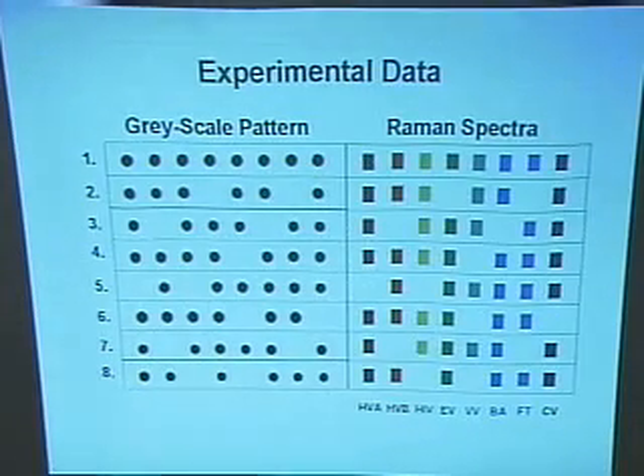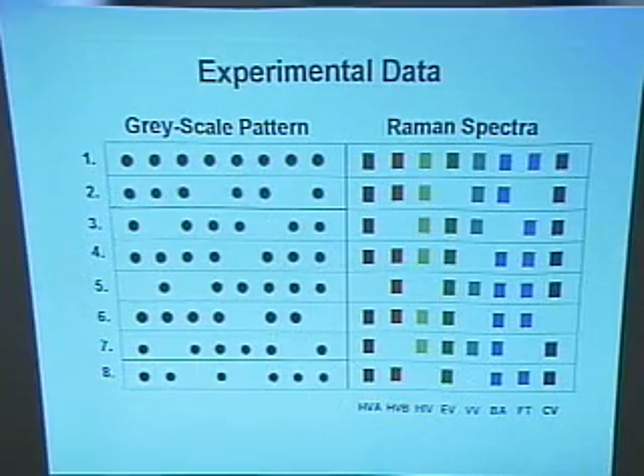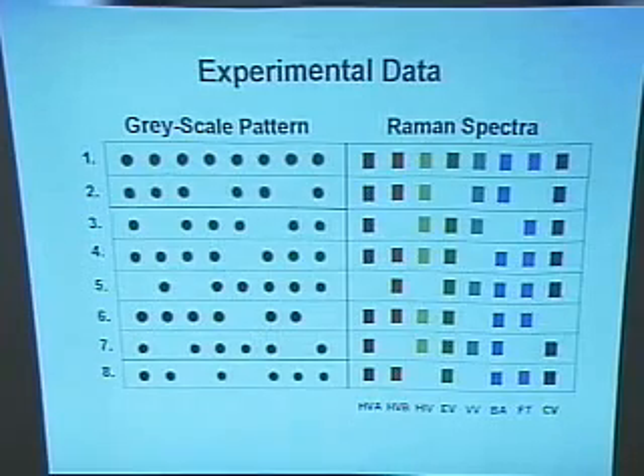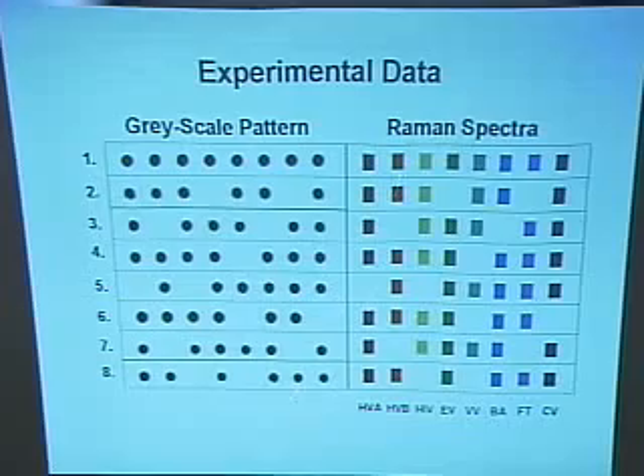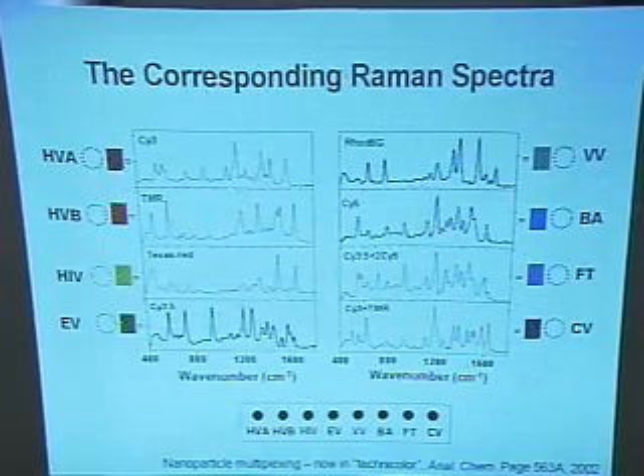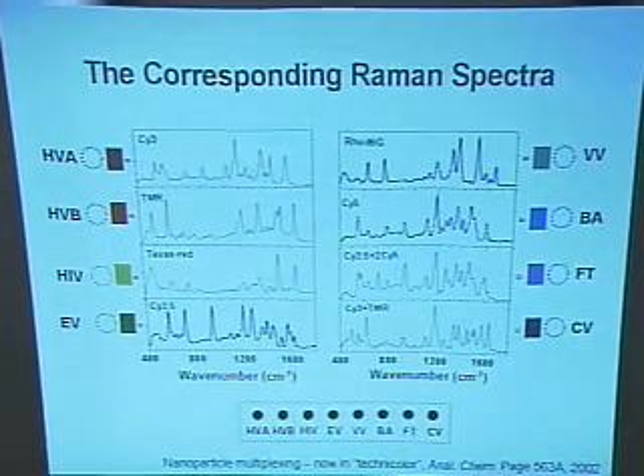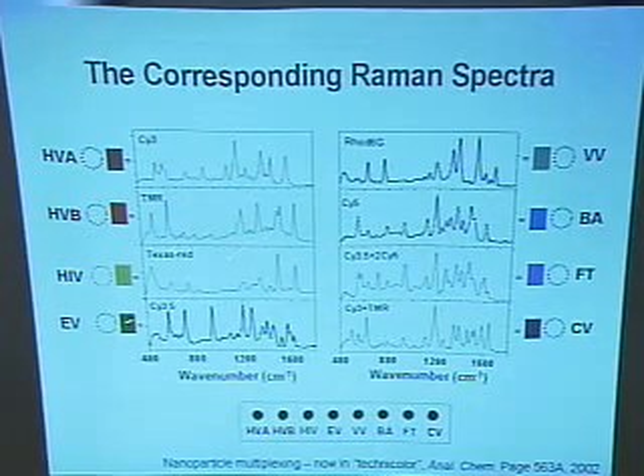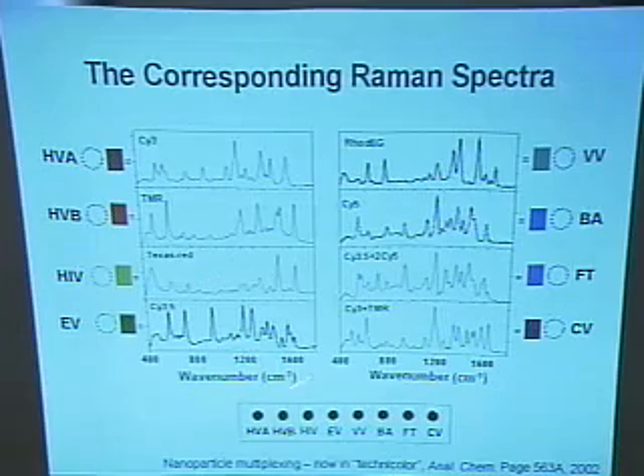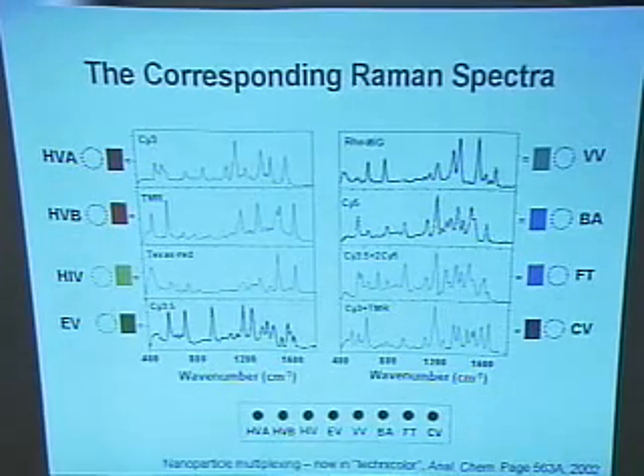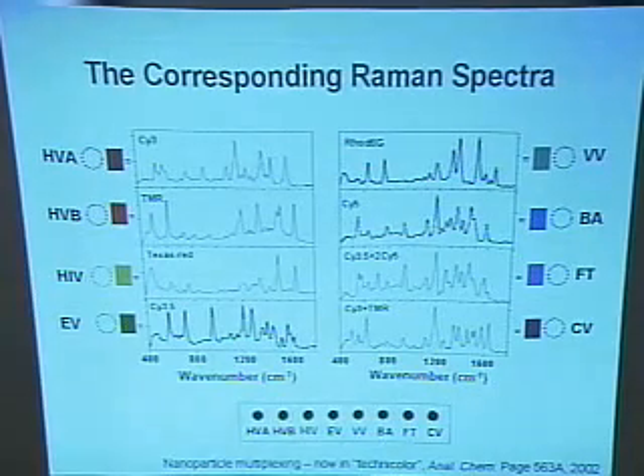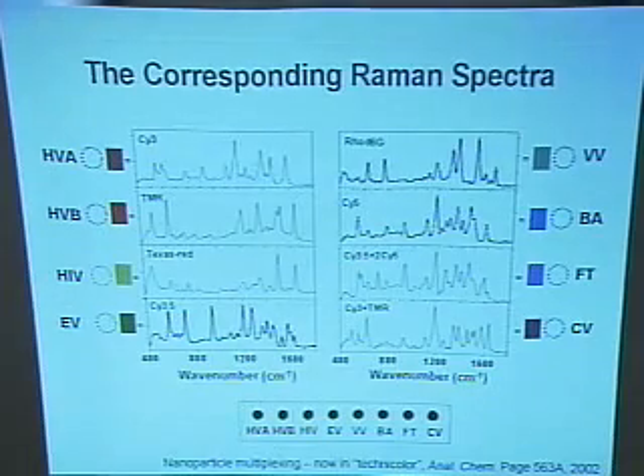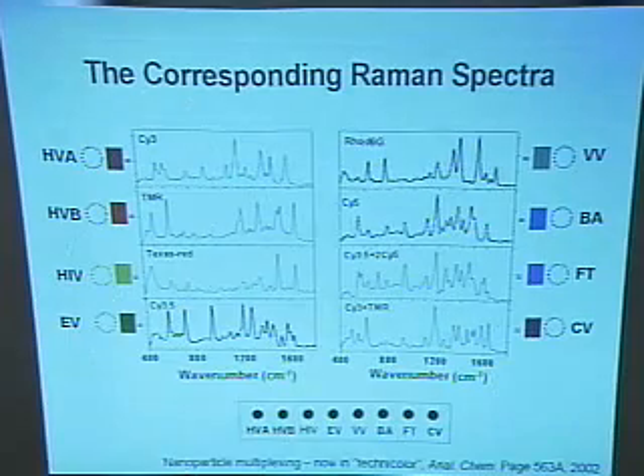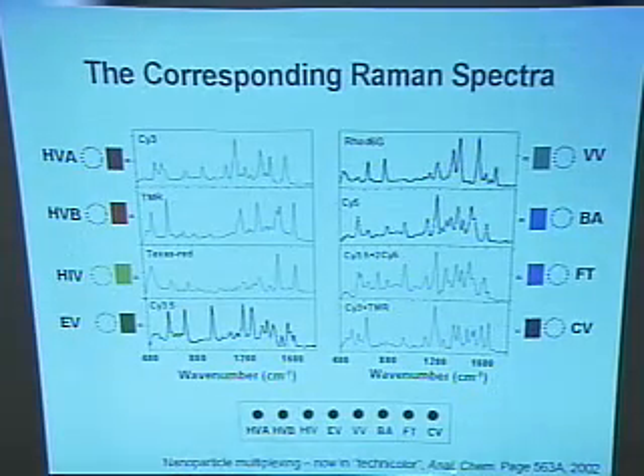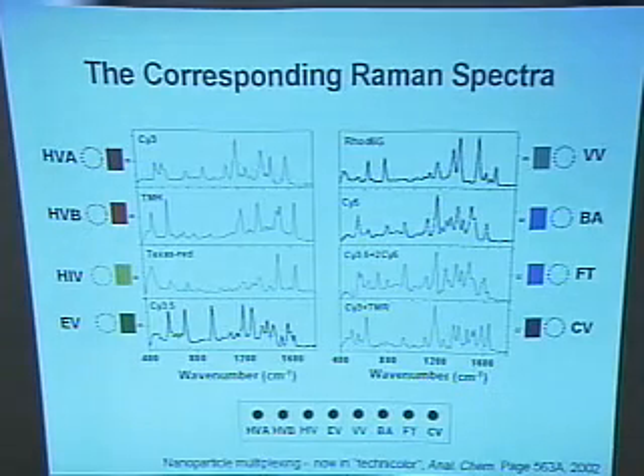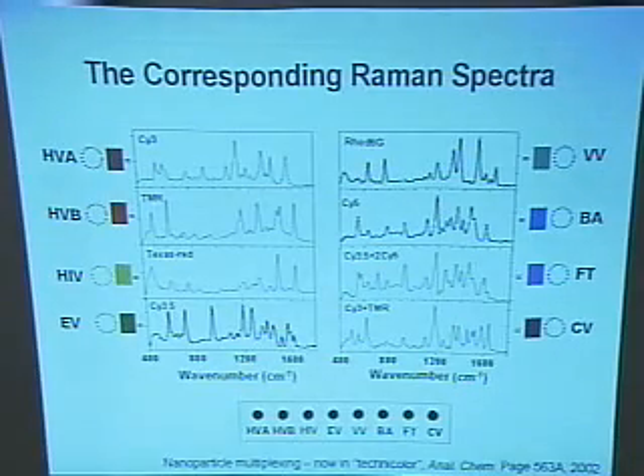Then you do the Raman spectrum. You will find the difference between each target, because on the probes you have different Raman labels. So this color has no meaning until you get their real Raman spectrum. By carefully checking each spectrum, we found in this chip-based detection we do not have cross-hybridization, which information cannot be provided by this black and white 2-color system. This color scheme is called, actually not by us, it's a guy in analytical chemistry who called it Technicolor, but not the Technicolor from the movie. But this is nice.